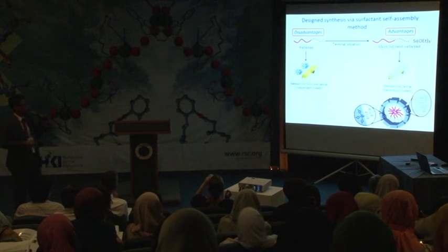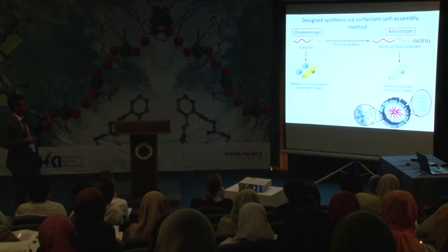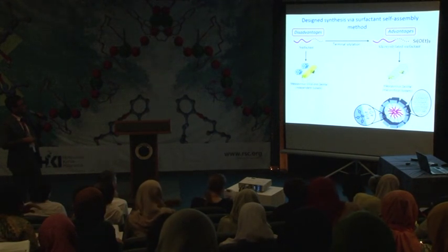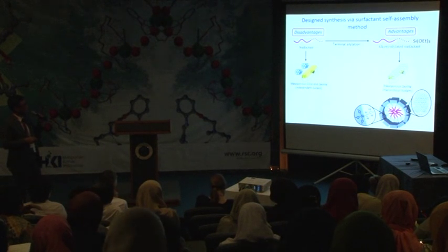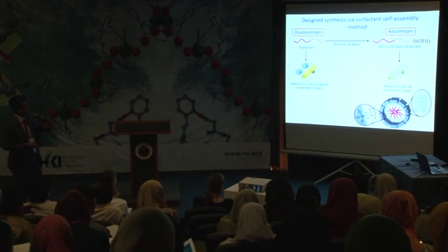That means we have to link the micelle formation and the zeolite nucleation and crystallization. This is the idea. If we do that, we hope that we get these materials. If we don't do that, and just take the normal surfactants, probably the nucleation will go separately into these physical mixture materials.